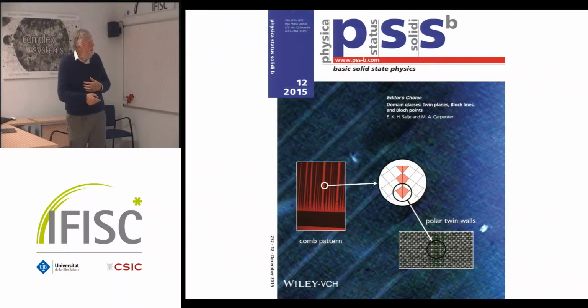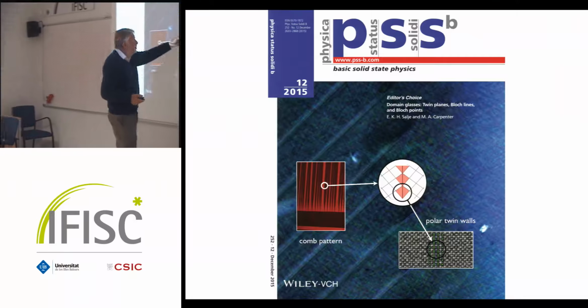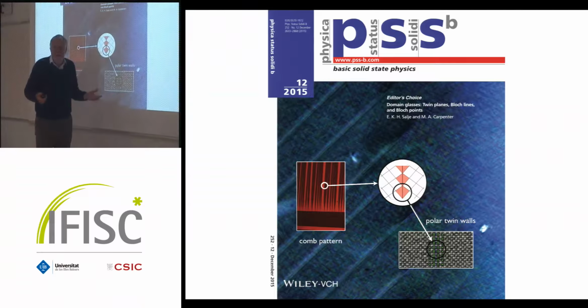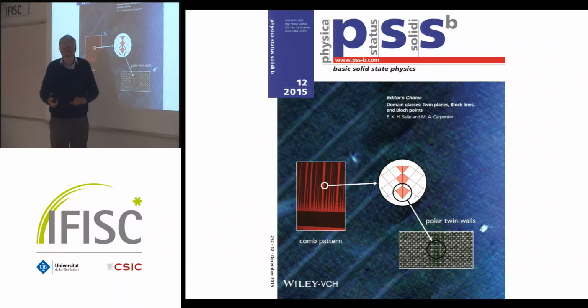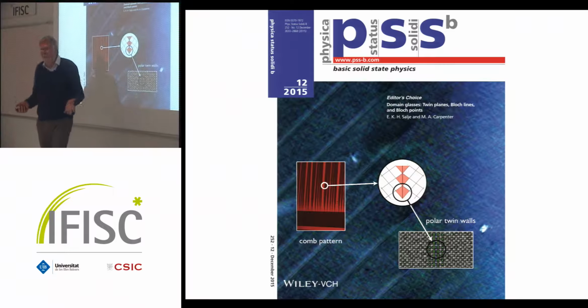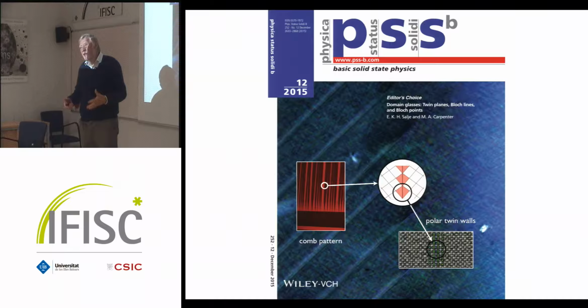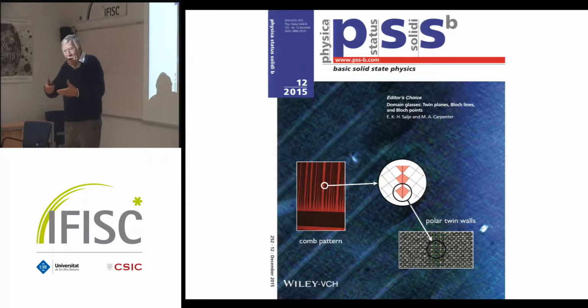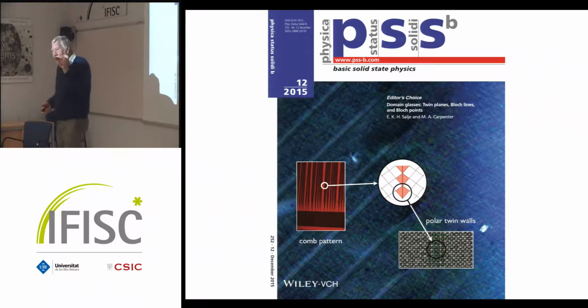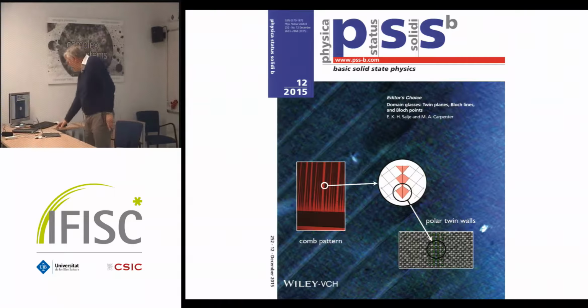And then, so, I mean, Twin was known. There are about, I would say, 200 papers on twin. They're known. But the question is, what is the functionality of the twin? And now we know because walls, they're tiny little walls hidden everywhere here, they have functionality. Twin has functionality. So what you do then, you do a PFM experiment, and look for the functionality, and then you find it, which is not surprising. But first you have to understand that you have to look for functionality in these materials.